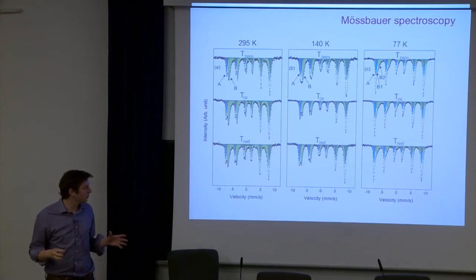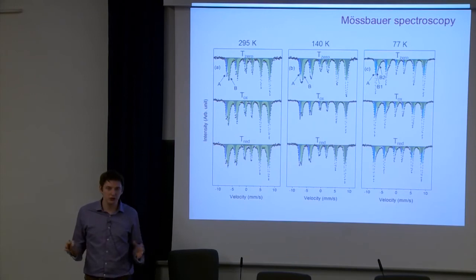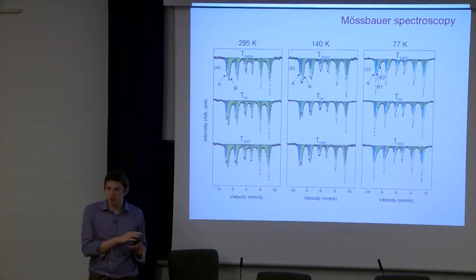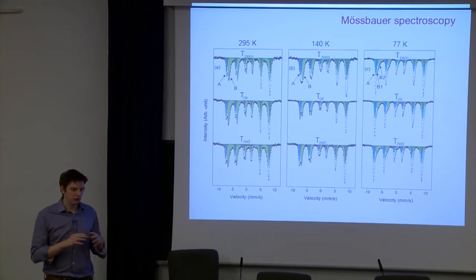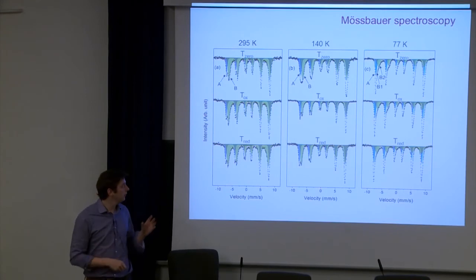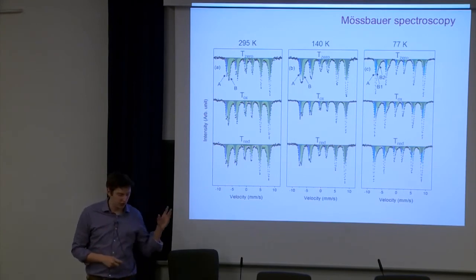And for those of you who are familiar with the Verwey transition, at the moment I'm thinking this is probably what's happening: as we're approaching the Verwey transition, there is some change in the electron hopping capabilities of the magnetite, and it's been induced by the oxidation of the sample or the reduction of it.